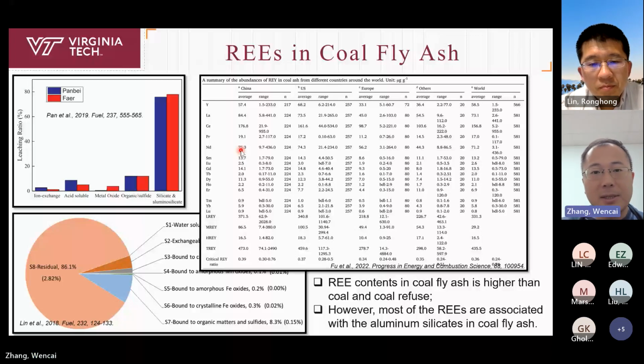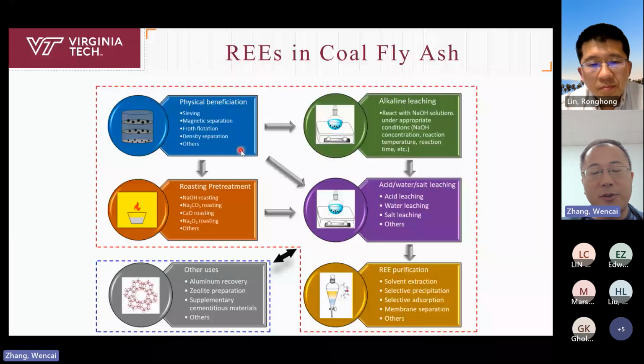So this is a figure in a review article that I published with other people. This is my understanding about how you want to recover rare earths from coal fly ash. So first of all, you can do a little bit of physical separation because it has been proved that rare earths can be concentrated to a certain degree by physical beneficiation. In most cases, rare earths are more enriched in the non-magnetic fraction and also the fine size fraction. So which means that if you use magnetic separation and sieving, you can get a fraction from the coal fly ash with a high rare earth content.